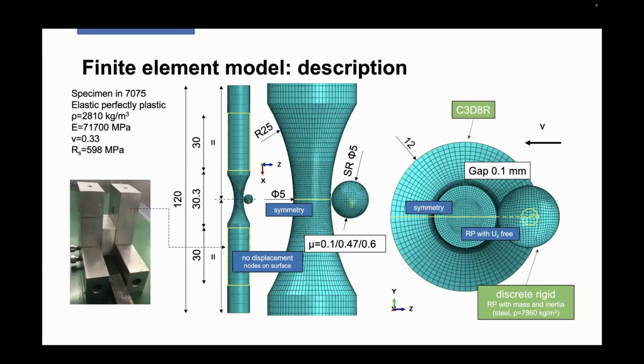Here we have the finite element model created for the impact simulation. We have the hourglass specimen that is made in aluminum alloy with the mechanical properties reported. We used an elastic, perfectly plastic behavior. And then we have this sphere that is modeled as a rigid component. And so the material and inertial properties are set to the center of the sphere. The boundary conditions are based on the test rig that we have in our lab. So the cylindrical parts are fixed in the specimen holder with 2 set screws. And we have placed the sphere very close to the hourglass specimen because we are neglecting the effect of air and gravity.